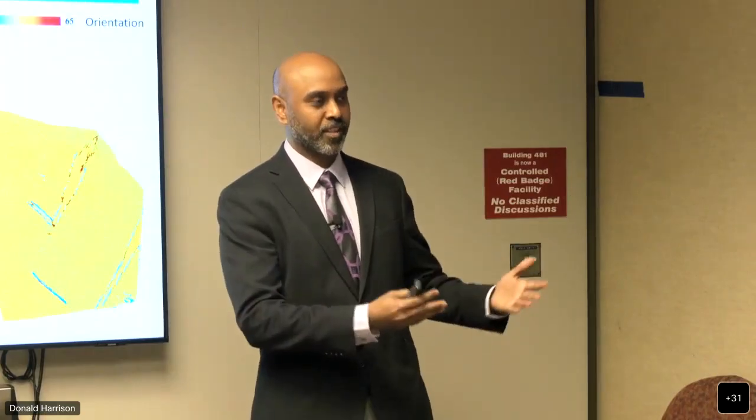We can set up the models. We could start saying, would you check this? Is this design going to go through that diamond formation, where it just complicates the interpretation of the experiment immensely? So I'll say this: we can set up a model to do a two-stage compression or a ramp compression as well. We can use the potential for diamond as well. Now the question is, is the formation of nanodiamonds triggered by the plastic? Is it just the wave effects, the pressures that are generated, or is it the pressures and the temperatures that are generated over there?